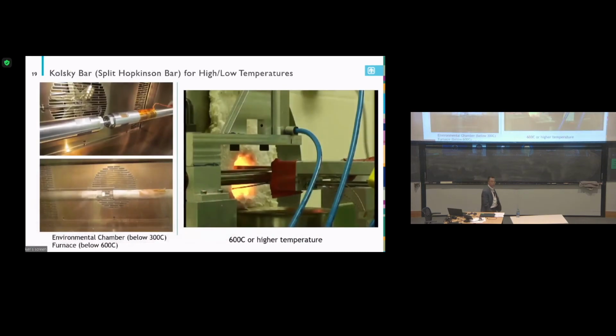And another thing is temperature. Sometimes the extreme environment is coupled with temperature, and people really want to understand how the material behaves under both dynamic loading and an extreme environment, low temperature, high temperature. So usually we use an environmental chamber for the high and low temperature. In my lab, usually we can do 300 degrees C and as low as minus 150 degrees C. That's very straightforward. We just put a sample into the environmental chamber and run the same dynamic test.